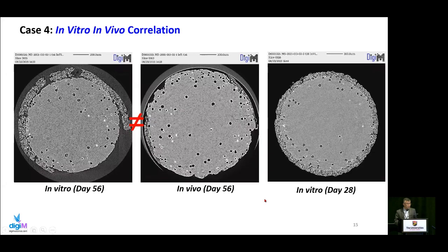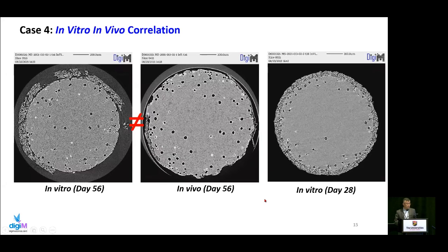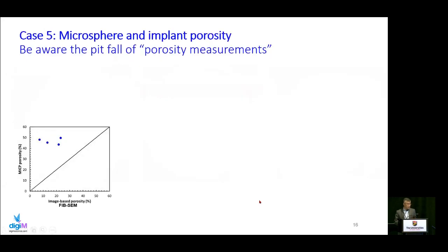So coming back to porosity measurement, this is another great collaboration with Dr. Burgess' team, where we are comparing the porosity characterization from these microspheres with a more conventional method, in this case, mercury porosimetry. Right? This is cross correlation, and we can see the conventional mercury porosimetry is fairly consistently 2 times higher than our image-based measurement.